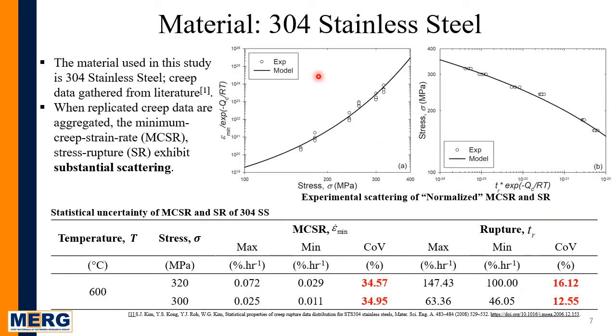For this study, we are taking 304 stainless steel, and the replicated creep data are gathered from the literature. The experimental scattering of these data is highlighted in this normalized minimum creep strain rate and stress rupture plot. We can see that the replicated creep tests show substantial scattering. To quantify this scattering, the coefficient of variation for the minimum creep strain rate can go as high as 34%. For the rupture time, the coefficient of variation could be as high as 16%. So this considerable scattering in the replicated creep tests needs addressing.